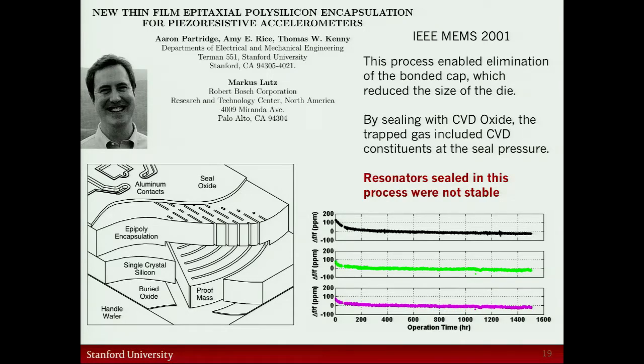And we knew right away the goal initially was to make accelerometers, make them small, and not otherwise destroy the performance, and we had some good success with that. But we knew right from the start that anything we built had some stability issues. The resonators that we could build in the same process had this drift that I showed earlier, and it had to do with the sealing process. We're using a chemical vapor deposition oxide to sort of plug up all the holes in the top layer at the last step of the process.